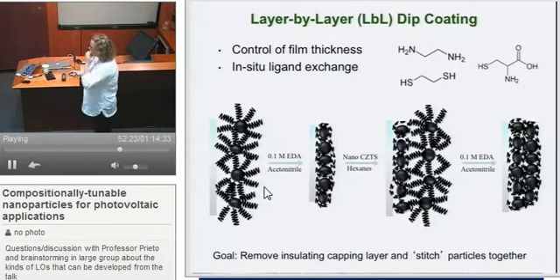Then we dip it in another solution of a high concentration of some short chain linker, something like ethylene diamine. The idea here is that you have a polar head group on both sides so that hopefully some of the time it sticks to two particles and stitches them together. These kinds of ligand exchange reactions are all equilibrium. This is something that freshmen and sophomores can think about.